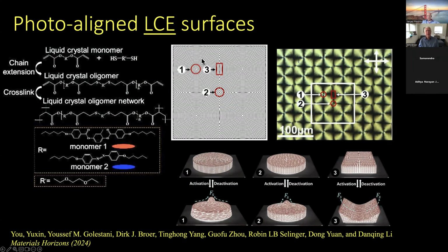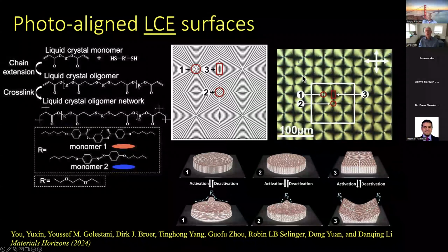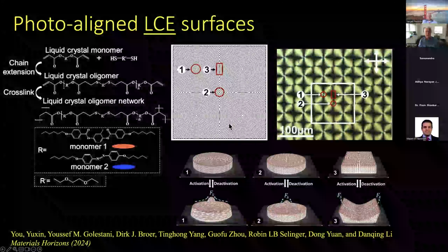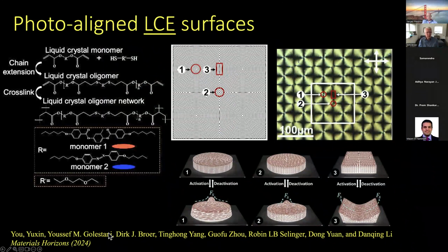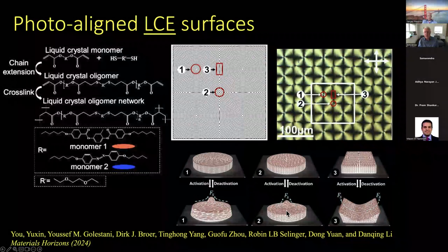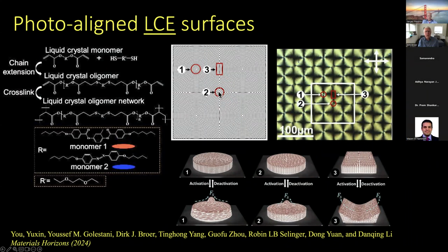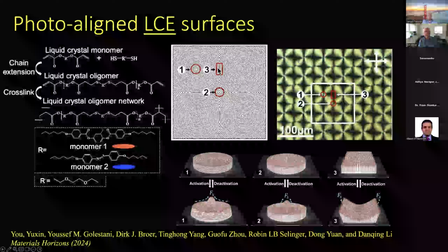And if you make this film and you look through the optical microscope, you should see a structure like this with the various defects, the control defects in the systems. Well, you can already model, and this is done by Yusuf in our group, you can already model that using these mating structures: you have expansion in these areas and this defect. You will have also expansion in these defect positions, and you will have shrinkage in these areas.